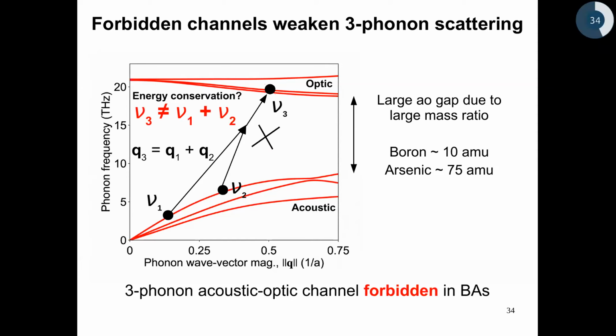The second constraint is the conservation of energy. So what it says is that the outgoing phonon's energy should be equal to the sum of the incoming phonon energy. And in this case, because of the large gap between the acoustic and optic phonon, this process is completely forbidden. That is, you cannot find any 2 acoustic phonons that can scatter into an optic phonon.